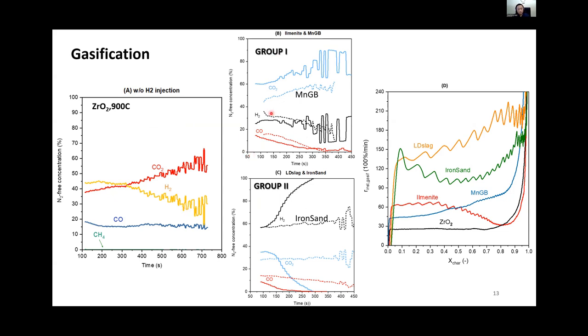The gasification with oxygen carriers can be divided in two groups. Group 1 is ilmenite and the manganese ore, and group 2 includes the LD slag and the iron sand. In group 1, CO2 is the highest, but in group 2, hydrogen is the highest. So you can see the difference. And the further comparison is in this figure D, and clearly LD slag and iron sand have a higher gasification rate than ilmenite and manganese ore, and all have a faster gasification than zirconium.